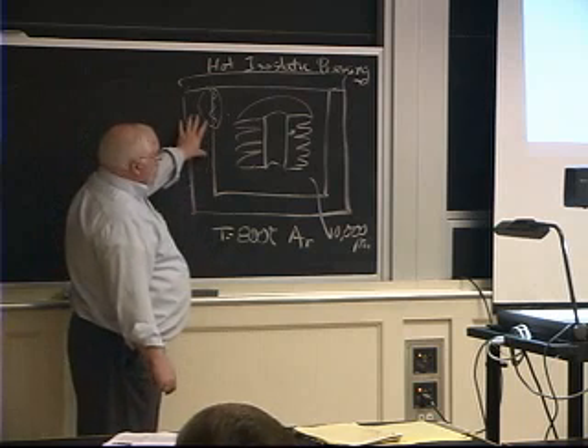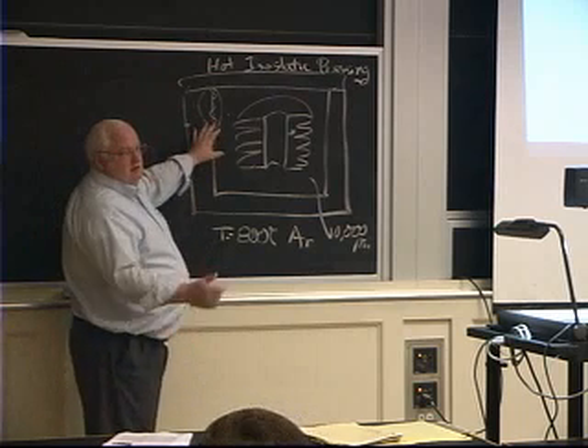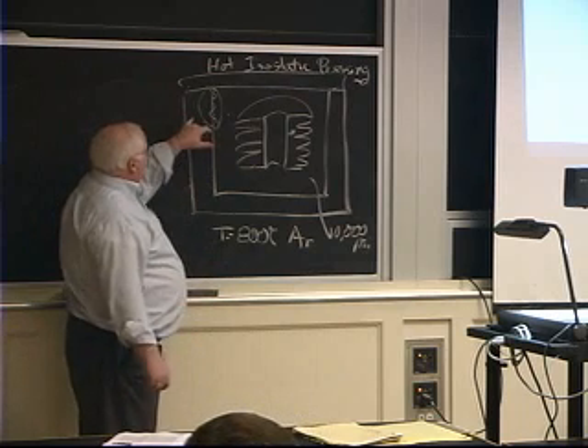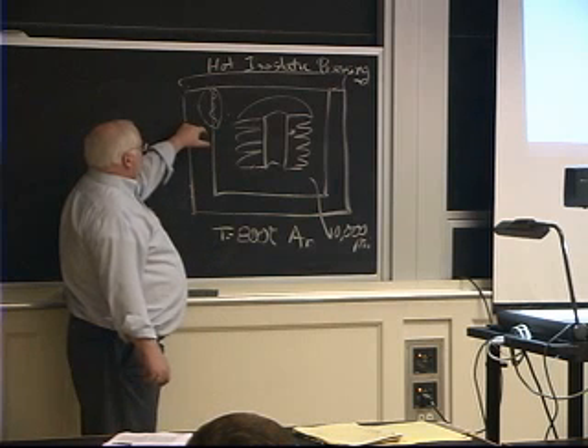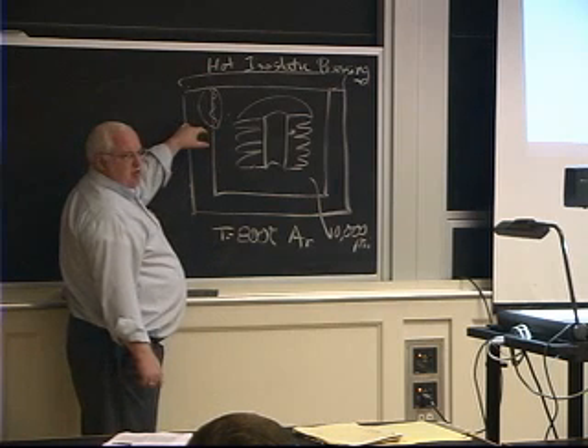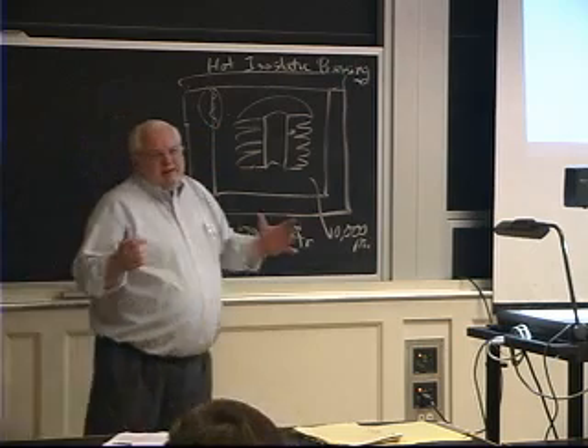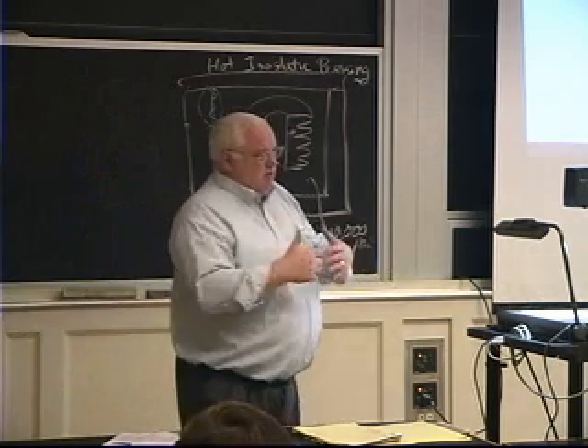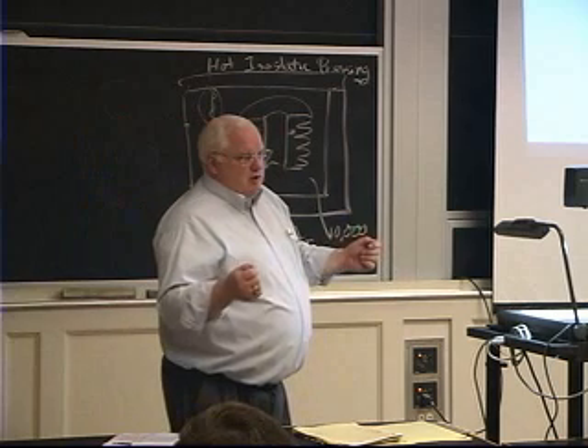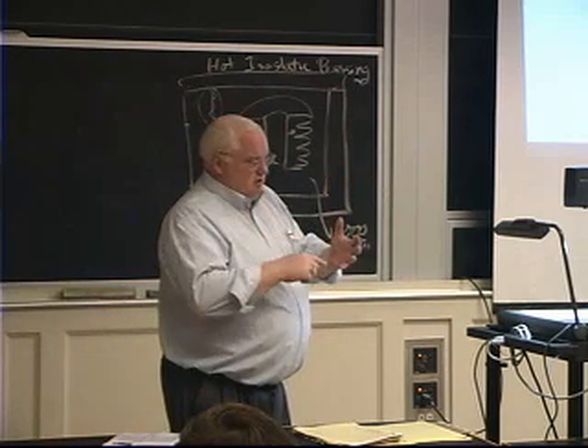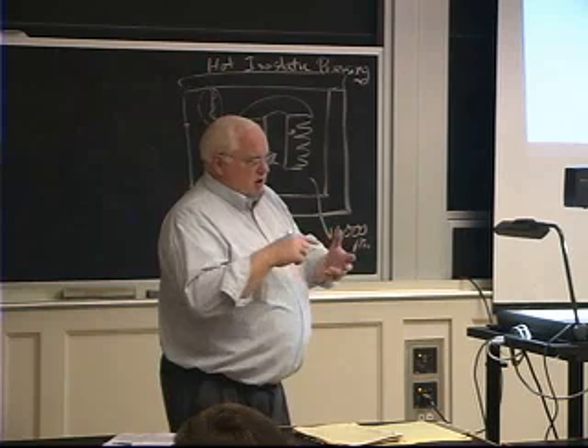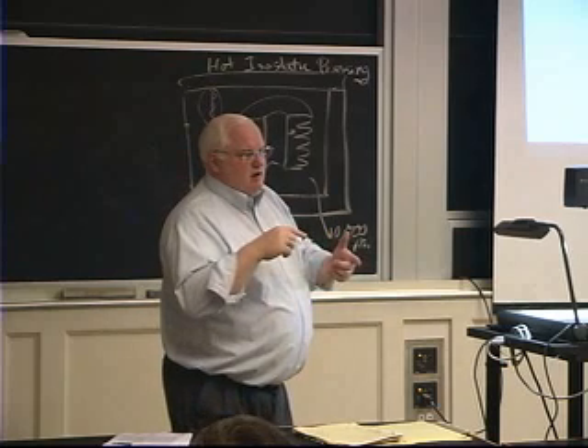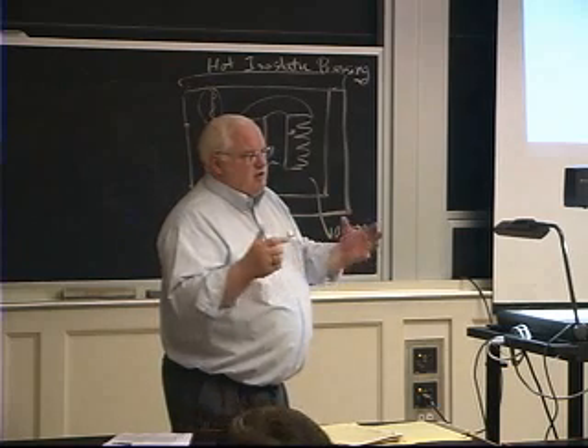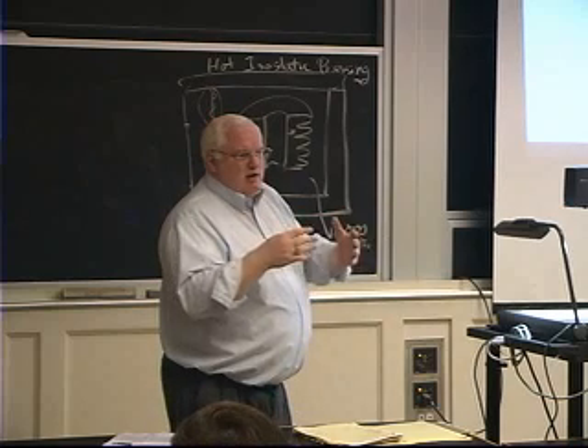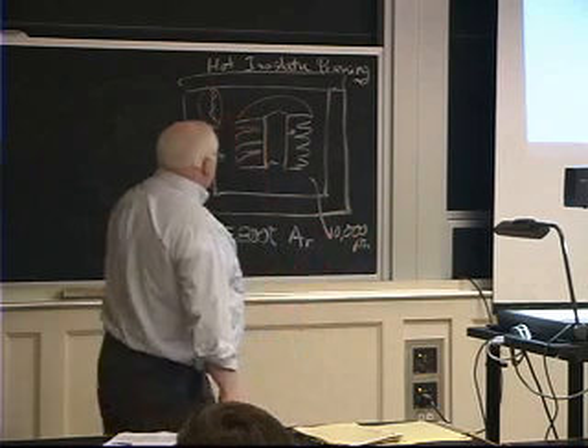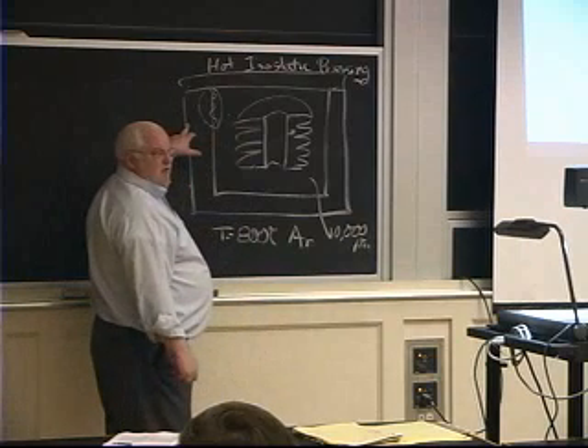But anyway, it turns out when they measured the properties of this after it had been destroyed, they found it still didn't meet spec. So lousy material properties, corrosion on the outside, corrosion generates hydrogen embrittlement. This thing should have had a critical flaw size of like 8-10 inches before the thing would let go in a brittle failure. Because of all these different 4 or 5 factors, hydrogen, corrosion pitting, lousy mechanical properties, transient thermal stresses, each one of them keeps chipping away at that 8 or 10 inch critical flaw size and makes it smaller and smaller. I measured the critical flaw size at the origin as half an inch.